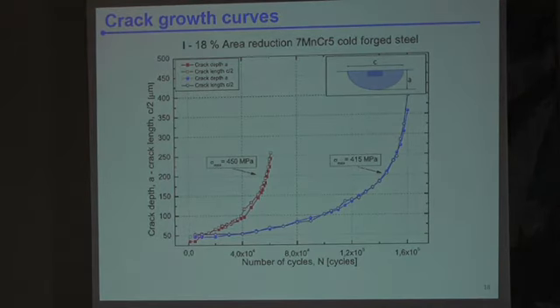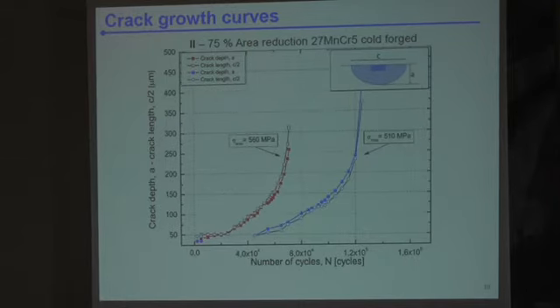Right, before going to the crack aspect ratio, a few more quantitative data. This is the crack depth, A, or the crack length, C, divided by 2 at the surface. So full symbols are depths and empty hollow symbols are the crack lengths at the surface for two different load levels, and you see that the curves superimpose, telling you that it's indeed a half-penny shape, and it doesn't depend on the stress level. Same thing for material number 2.